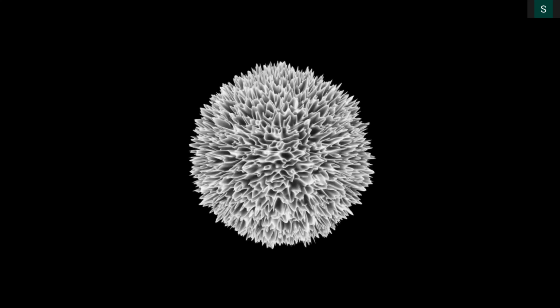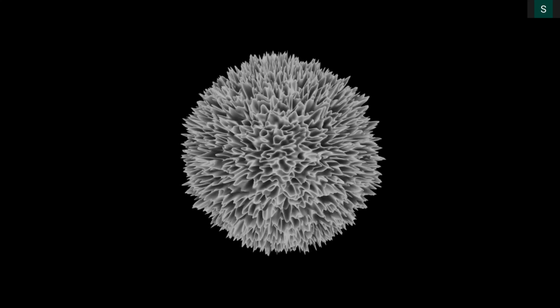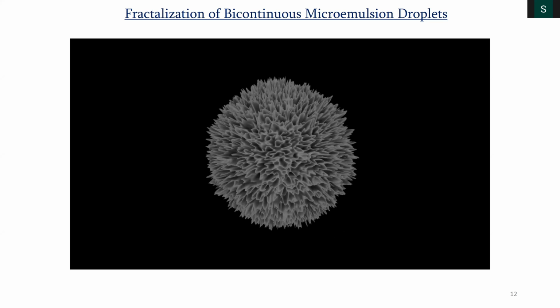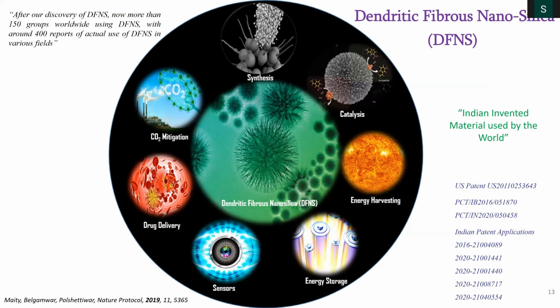That means if the fibers are less, they will go away from each other. If fiber density is more, they will come together with each other. And you can tune the pore size distribution by that. Right, so this material is used worldwide now. This is our invented and patented material, which is used by 150 groups worldwide, not only for catalysis and CO2 mitigation, but the question asked about the drug delivery. So lots of work about drug delivery, but you can imagine they are porous, having a tunable porosity. So you can load the drug and selectively release. They were also used in sensors, energy storage like batteries and supercapacitor, and energy harvesting, which is ideally part of the catalysis.